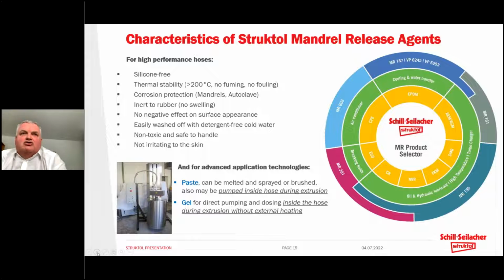The lubricant should be matched to the rubber so it doesn't swell and therefore doesn't damage the surface appearance. We expect them to be easily removable. And of course, the operators have direct contact with that, so they should be non-toxic, safe to handle and not irritating to the skin. And finally, as mentioned, we have newer technologies where we can spray these lubricants directly into the hose during extrusion, and we can remove the dipping process completely.